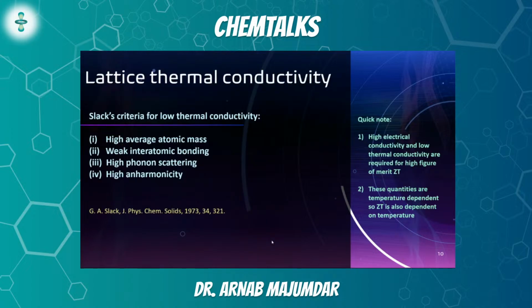But before I go on to the material that we studied, it's absolutely quintessential that we talk about how we can achieve low lattice thermal conductivity. So quite a few years ago, 5 decades in fact, Slack came up with 4 different criteria for achieving low lattice thermal conductivity. The first one being that the whole system should have high average atomic mass. The second being weak interatomic bonding. The third being high phonon scattering. And the last one being high anharmonicity. Now, we have to keep this in mind. In all the later slides, I will keep showing these 4 criteria and whether we are satisfying them or not. If these 4 criteria are satisfied, there's a very high chance that we will be able to predict very low thermal conductivity for a material. Okay.